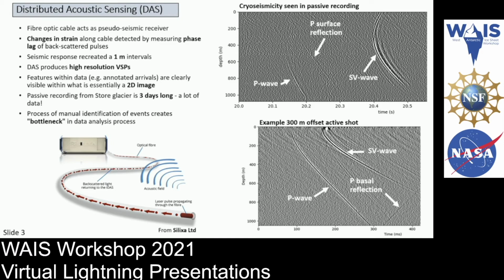Here we see some examples of data that was collected with this DAS system on Store Glacier. At the top, we have examples of cryoseismicity seen within the passive recording. You can see a P wave, an S wave, and some reflections from the surface. And then underneath, there is an example from the active shot, in which we can also see a P wave, a basal reflection, and another S wave.